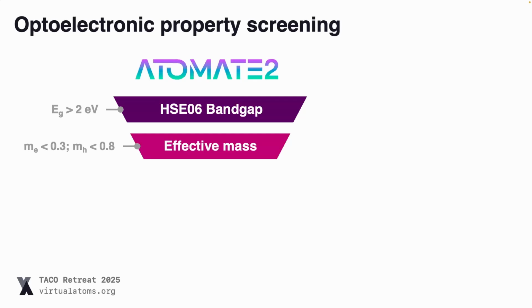And we filtered out those materials which had a band gap less than 2 electron volts. Again, we're interested in materials with a band gap of around 3.2 eV, so this is quite a conservative filter. And we also calculated the band structures and filtered out the materials with high electron and hole effective masses.